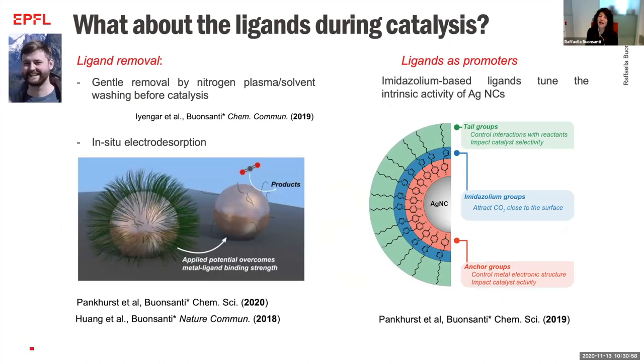Now, always talking about interfaces, I mentioned ligands before. So a question that comes up often when we discuss our work is, well, what happens to the ligands during catalysis? Do they have any effect? Now, in most cases, we do remove the ligands with some treatment before actually doing catalysis. In other cases, the ligands might desorb in the initial stages of the catalysis. But then what James started doing is also to play with the ligands and to use ligands as co-catalysts. So James comes from a homogeneous catalysis background. And normally in homogeneous catalysis, you do use ligands to modify the behavior of your catalyst. And so he joined the group and we started to explore this possibility.